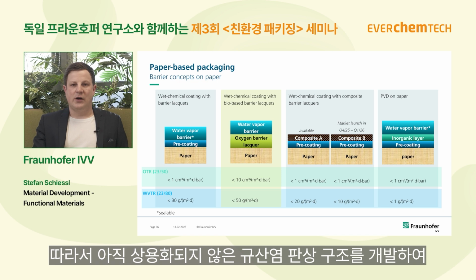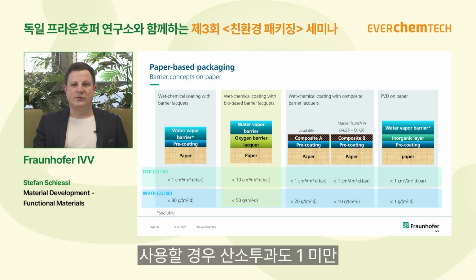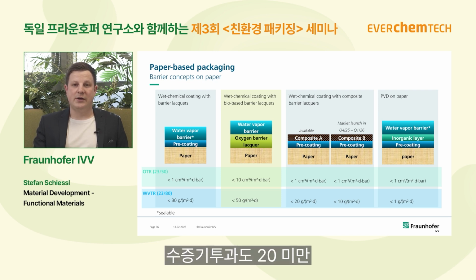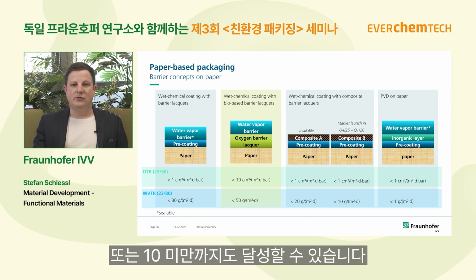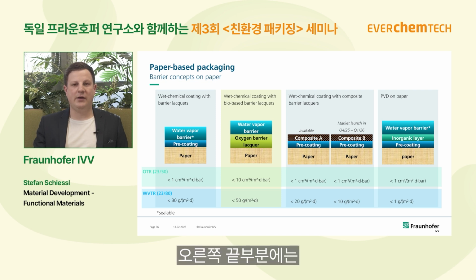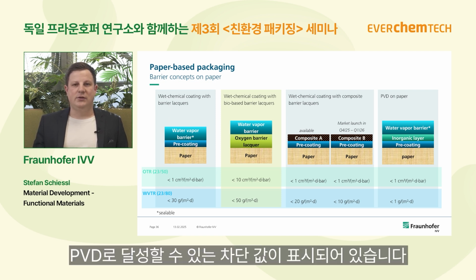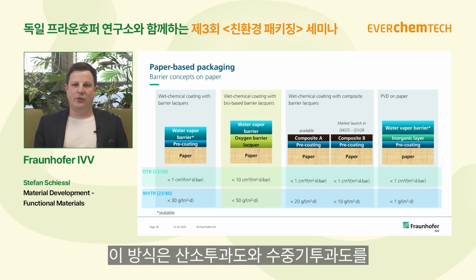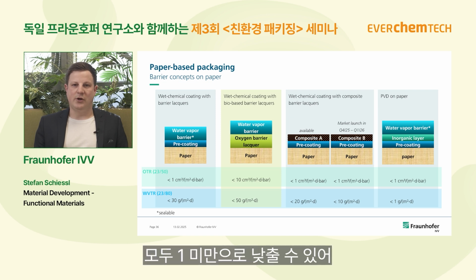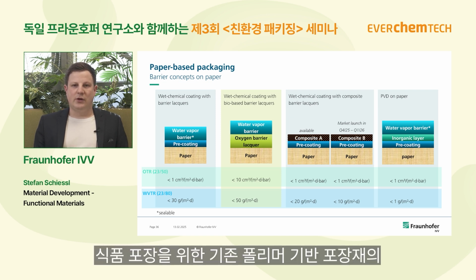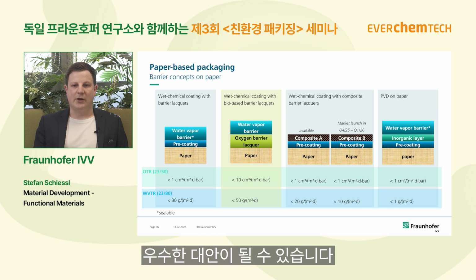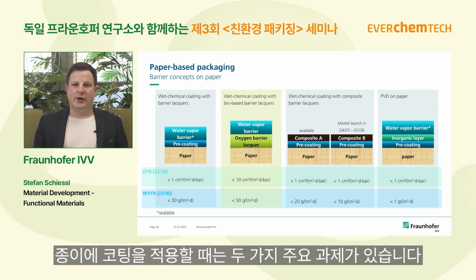So we are able to reach here also oxygen transmission rates below 1 and water vapor transmission rates below 20, or even below 10 if we are working with very new silicate platelets that are not market available right now but in development stage. And on the very right hand side you see the barrier values that are possible to achieve with physical vapor deposition. Here both of the gases important for food packaging are below 1, which is a very good alternative for typical polymeric packaging.